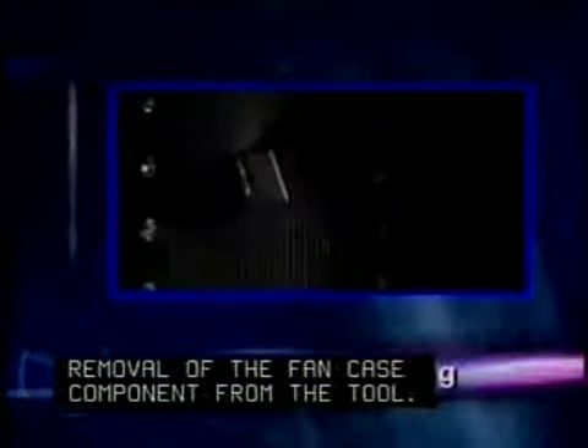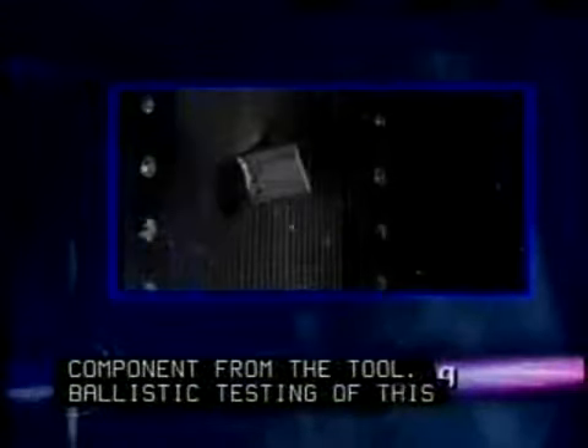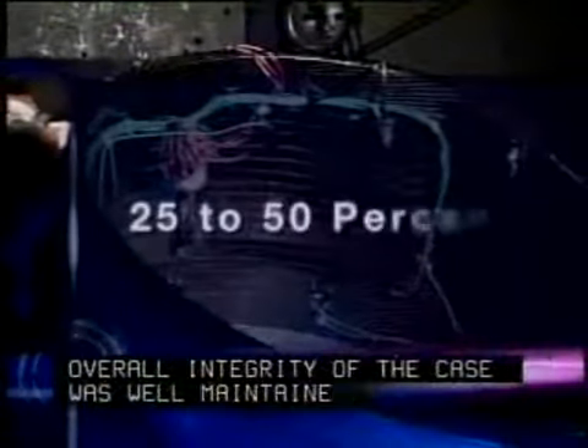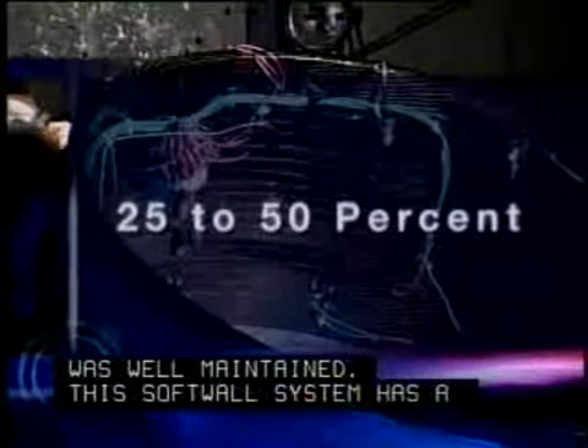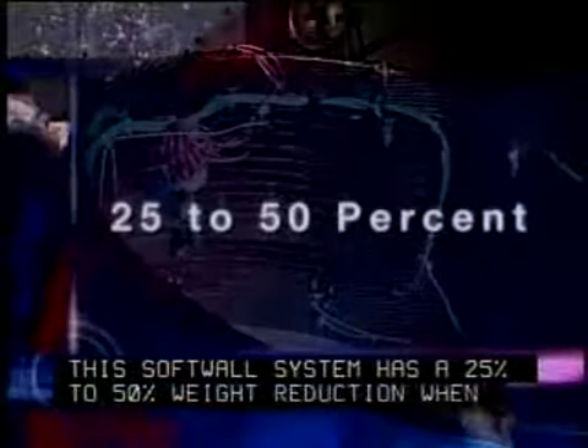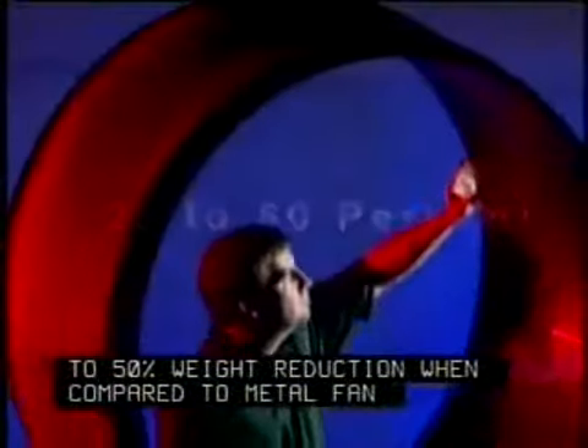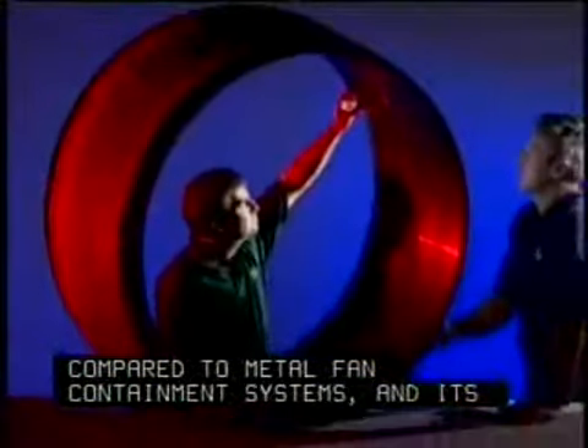Ballistic testing of this prototype showed localized damage where the fan blade penetrated the skin of the case, but damage was limited, and the overall integrity of the case was well maintained. This soft wall system has a 25 to 50% weight reduction when compared to metal fan containment systems, and its retention of mechanical properties during a projectile impact test was twice that of metal.